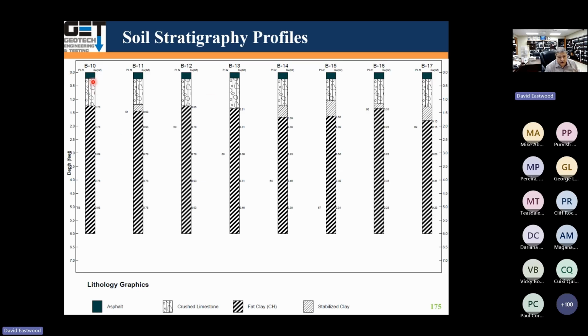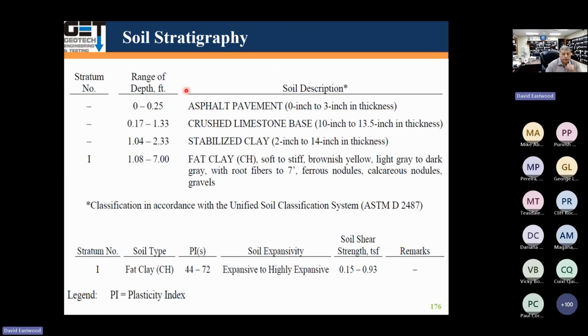And you can see in here, this B10, for example, has no stabilized layer. B11's got only maybe a couple of inches. B13 has got no stabilized layer. B12 has no stabilized layer. B15 has got some. B16 has got some. In general, we had 0 to about 0.25 feet of asphalt paving, 0 to 3 inches in thickness.